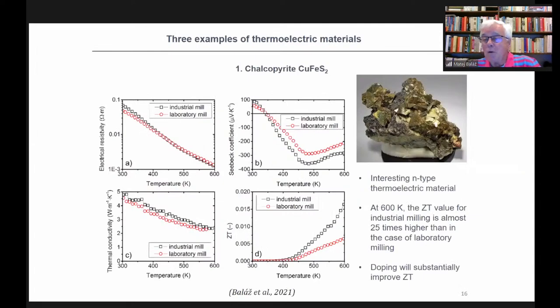And now, at the end of my presentation, I will show you 3 examples of thermoelectric materials. The first one is chalcopyrite. Chalcopyrite is a very well-known source of copper. My PhD work was on leaching or hydrometallurgical treatment of chalcopyrite under mechanical activation. But in this case, it's another story, because it's a quite interesting N-type material. N-type, you see the Seebeck coefficient here is negative.